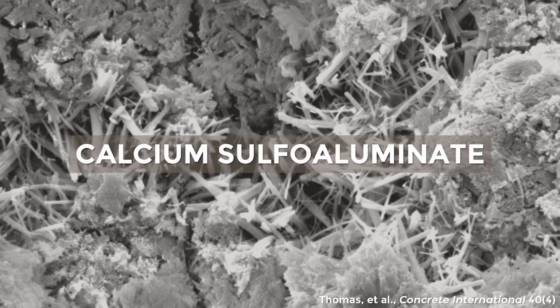Okay? Calcium sulfoaluminate cement is quite special because it reacts to form what you see here on your screen. This is our second scanning electron micrograph, and what you see is a needle-like structure. It's the hydration product of calcium sulfoaluminate cement, and it's called ettringite. Ettringite's really interesting because it, and by extension calcium sulfoaluminate, reacts very, very quickly.